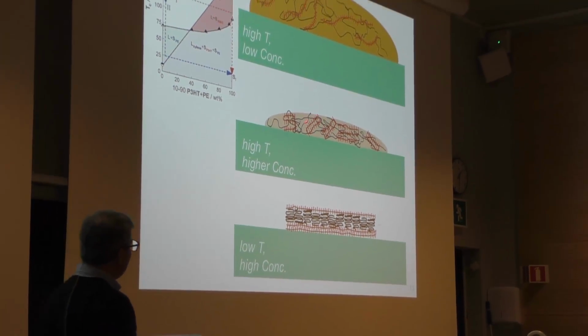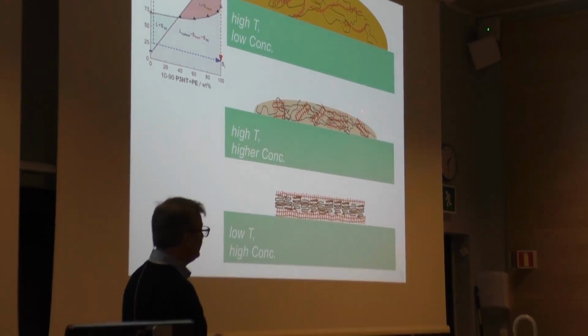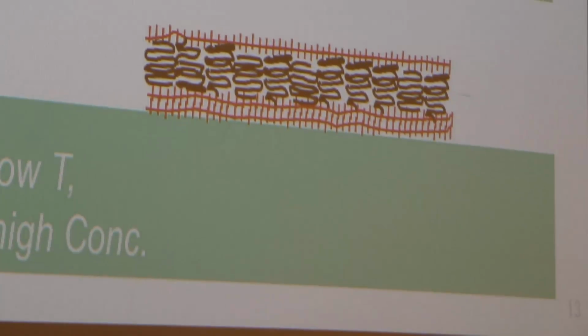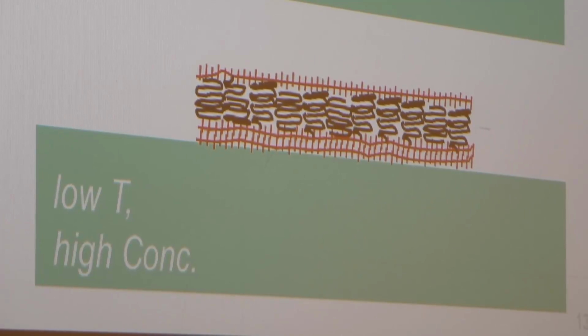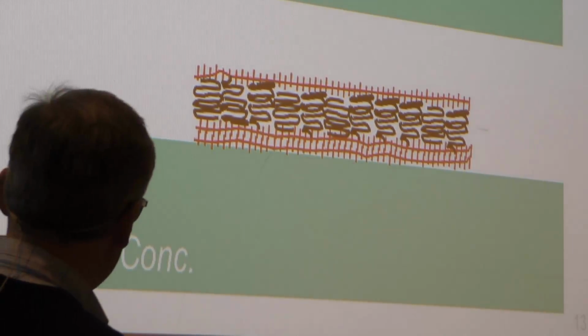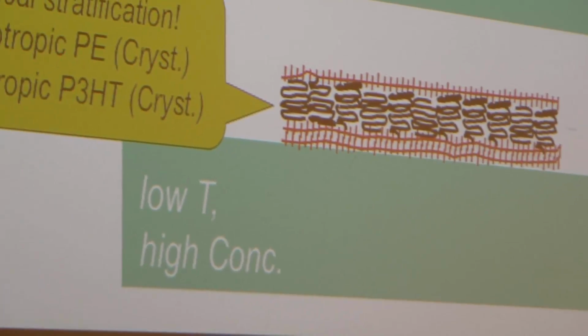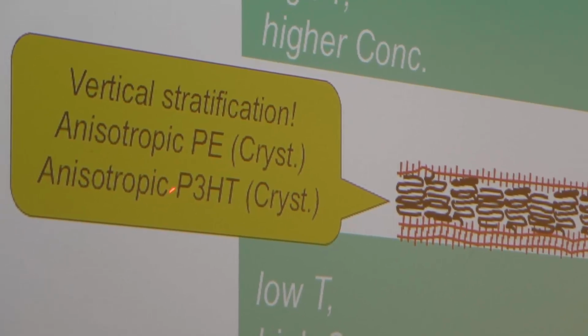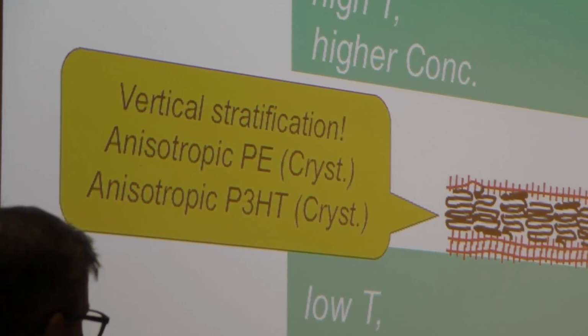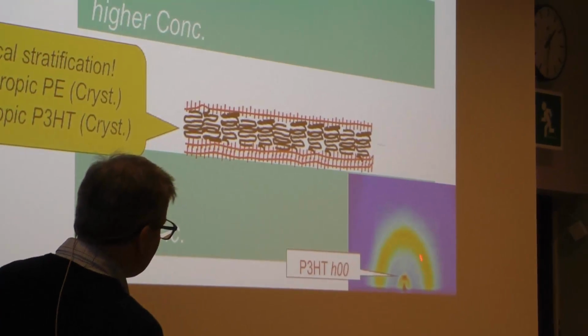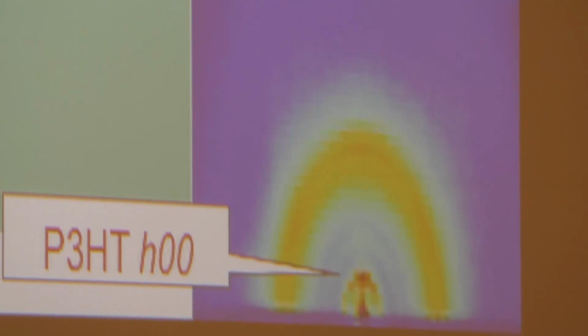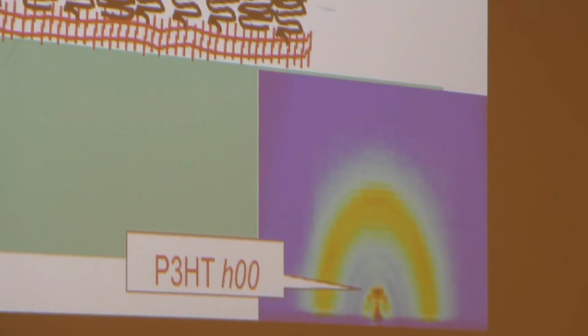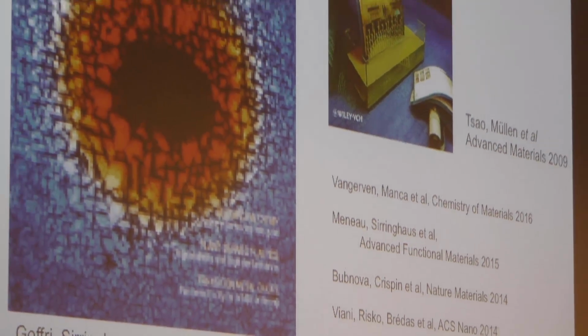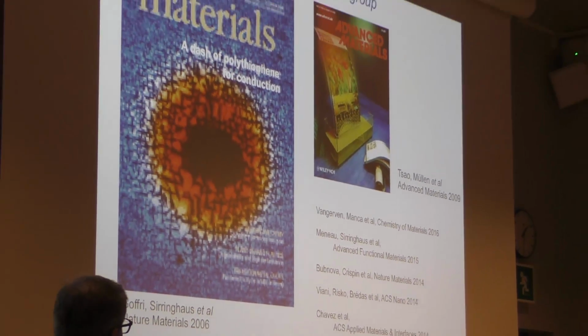Following the other route, the polythiophene will crystallize first, and then when the polyethylene crystallizes, it will be kind of squeezed away. It turns out that this leads to vertical stratification, where the polyethylene is anisotropic, same with the polythiophene, and again we have evidence for this in the signature from the grazing incidence studies. So this was one example. It was published in Nature Materials in 2006.